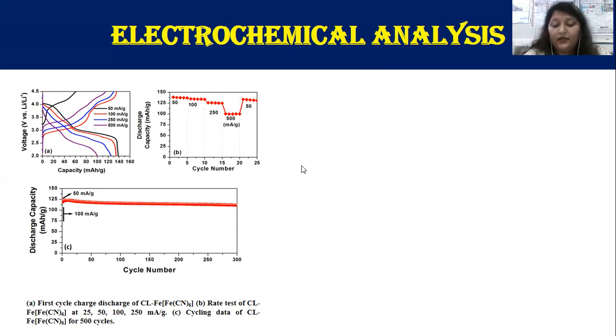So it would require a very high concentration of lithium iodide to increase the lithium content for chemical lithiation, as the reduction voltage dips below 3 volts. Hence, chemical lithiation using lithium iodide is not a suitable reduction process, and an alternative lithiation process is required. Nevertheless, this partially lithiated Prussian blue analog exhibits good electrochemical performance; the specific capacity in subsequent cycles and capacity retention for the long cycling performance are very impressive.